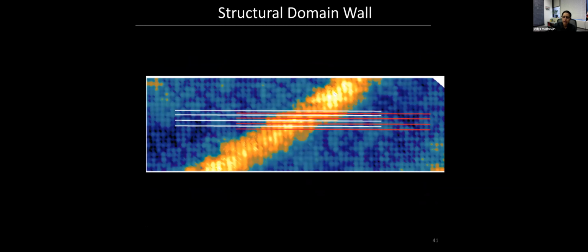To see that the atoms are shifted by half a unit cell, you have to zoom in, and you can either track the atoms by drawing lines, which is a pretty crude technique. But we've also done a more serious analysis using the phase and the Fourier transform. But essentially, whatever method you use, you can show that the atoms on the left side of this domain wall are shifted from the atoms on the right side of the domain wall by exactly half a unit cell. So this is exactly the kind of domain wall we're interested in.